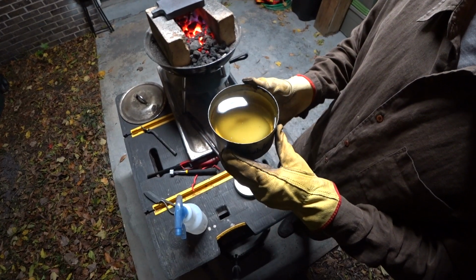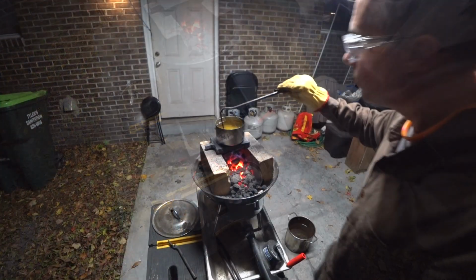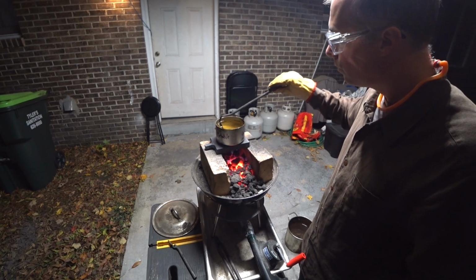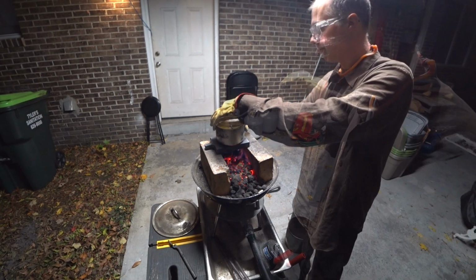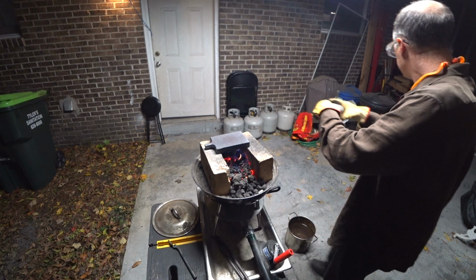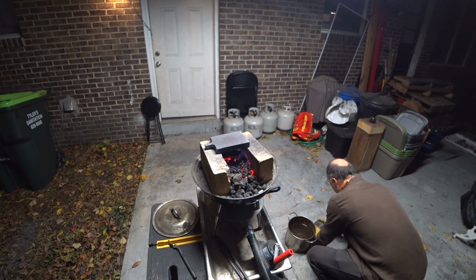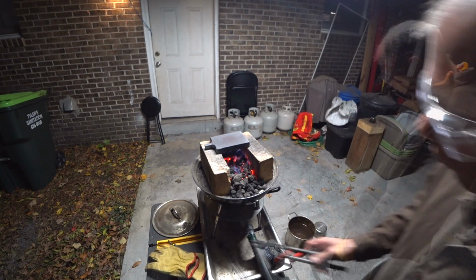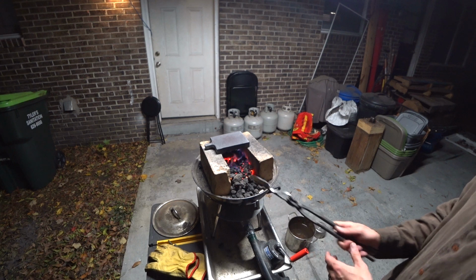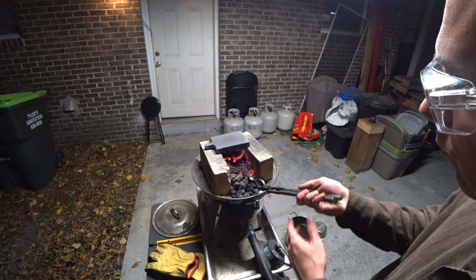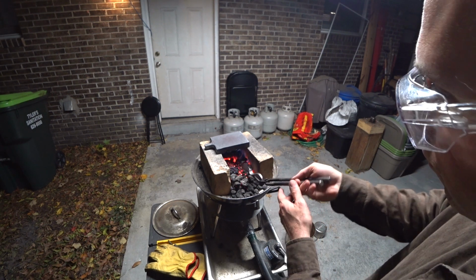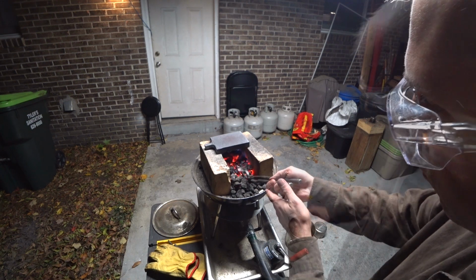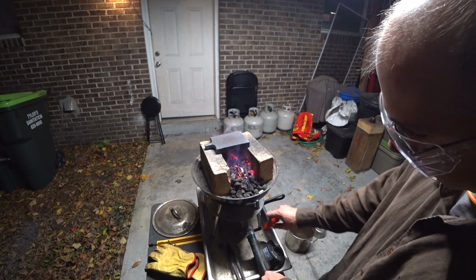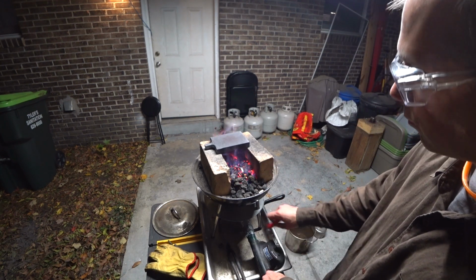Now this really reduces the likelihood of cracking or warping, and you still get the full hardness like you would if you quenched completely in water. Now, if you quench only in the vegetable oil, you will get a hardened blade. It's just not going to be full hardness. Trust me, I've actually done the experimentation, and in an upcoming video, I'll actually show you guys that.